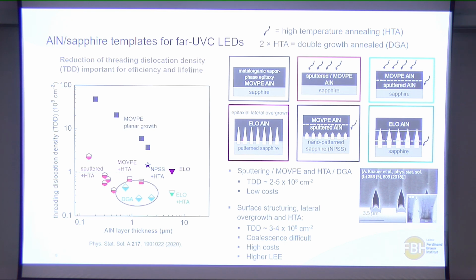What advantage this gives you is basically now you have some structures in your system. So this will help you to scatter the light out of your LED structure. So this is quite helpful when it comes to extracting light from your LED. The disadvantage of this approach, of course, is although you get a good and low threading dislocation density, it's quite expensive because you need to go now through a whole lithography process to structure the layers, and of course then the costs are quite high.